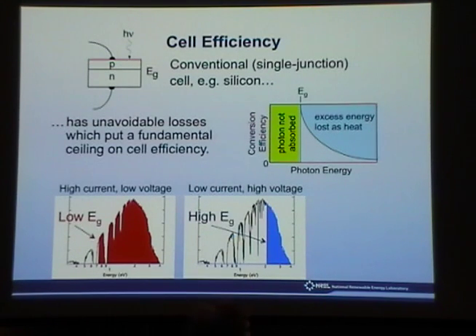And it's a simple optimization exercise for a given spectrum. For a single junction, the optimum band gap's about 1.4, about gallium arsenide, and you can get an efficiency of about 33%. But you can do a lot better with a multi-junction.